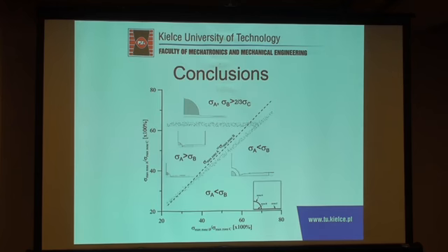So, instead of a conclusion, I put this picture in which there are results of these simulations. As you can see, if the cohesive stress in zone A and zone B is greater than 63% of cohesive stress for zone C, the cell breaks in the way the homogeneous cell would break, but there is only one extra feature, this protrusion on the surface of fracture.